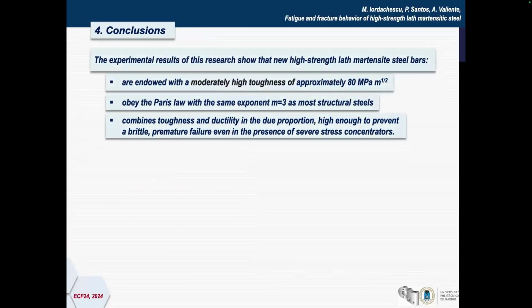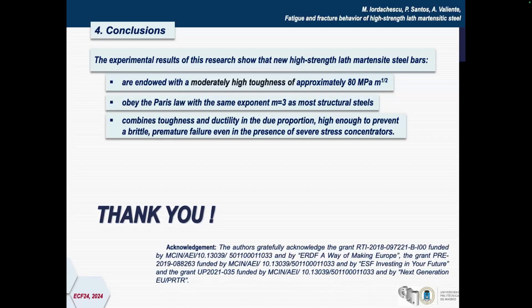So now the conclusions. The experimental results show that these martensitic steel bars are endowed with a moderately high toughness of approximately 80 megapascals square root of meter, obey a Paris law with the same exponent as most structural steels, and combine toughness and ductility in due proportion high enough to prevent a brittle fracture in presence of severe stress concentrators.